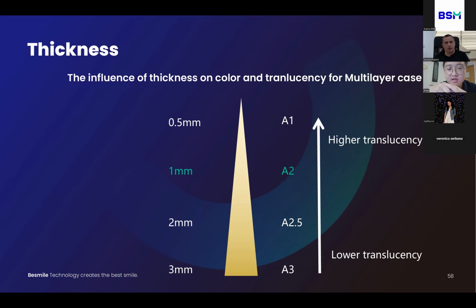For example, if you want to make an A2 implant bridge, we recommend using an A1 multilayer zirconia disc to make this bridge. Because the thickness is higher, after sintering the shade is close to A2.